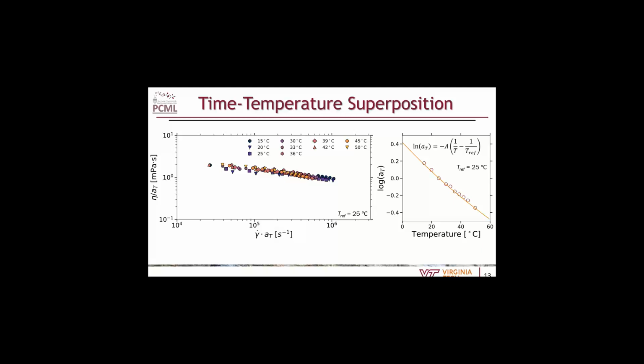This is really nice because where our previous data maxed out at just below 800,000 reciprocal seconds, we're now getting just above 1 million. And we've extended our lower shear rates a decent amount as well.